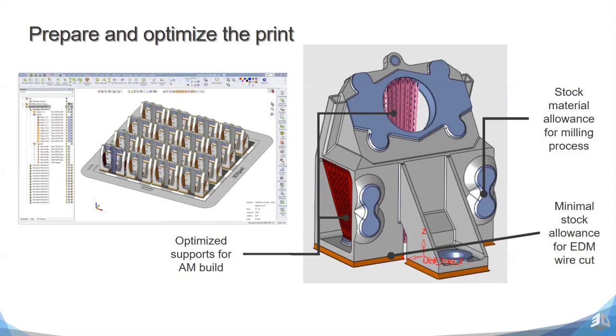And then we showed a couple of the darker gray areas where we optimized the design for additive and then added a little stock on there because the end customer wanted to have a super finish on these. Matter of fact, somewhere close to a bearing surface finish. So we added a little stock and produced the CNC code to have it post-processed to within the customer specifications.